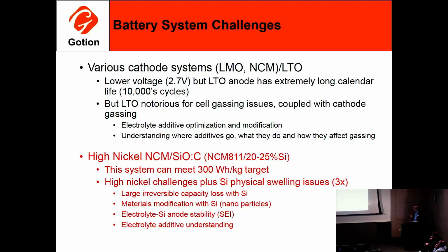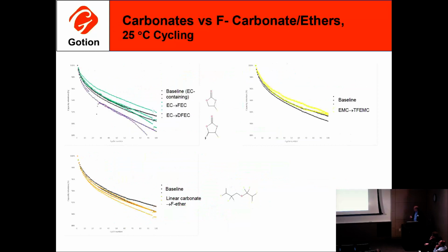So the goal here is to really look at, plus the fact that silicon has a known large irreversible capacity loss on the first 20 cycles. And so we're looking at this by changing the silicon material. We're collaborating with a couple universities on this. And then again, how do you create an anode SEI on the silicon-based material? And so this is just a quick look at where we're at right now. And again, from this, you can see if you take the baseline material, the irreversible capacity loss here cannot be fixed by electrolyte. That's a materials processing issue on the silicon that has to be fixed to get that flat out at the beginning.